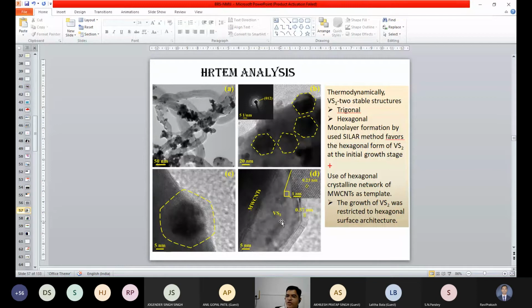So SILAR favors the hexagonal form of VS2 at the initial stage of growth, because the carbon nanotube has a certain hexagonal shape. Initially those hexagons develop on the carbon nanotube because of the monolayer formation. Because of that, we observed the hexagonal structure of the vanadium sulfide on the carbon nanotube because of dual things: one is the use of the carbon nanotube and the other is the use of the SILAR method. So that is the beauty of this work.